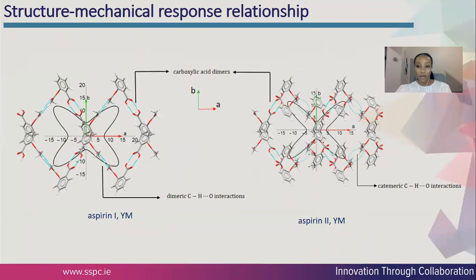Like with urea, we can look at the arrangement of the intermolecular interactions in a certain plane. What is shown here is the arrangement of the intermolecular interactions in the AB plane, overlaid with the Young's modulus in the same plane for aspirin Form 1 and Form 2. The interactions include hydrogen bonds holding the dimers together and the CHO contacts between the layers. The arrangement of these interactions forms a butterfly-like shape, which mirrors the shape of the Young's modulus. More so, the directions of the interactions coincide with the direction of the largest resistance of the Young's modulus, suggesting once again that the hydrogen bond confers extended strength to the Young's modulus.